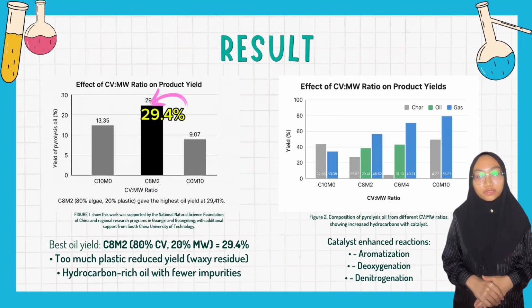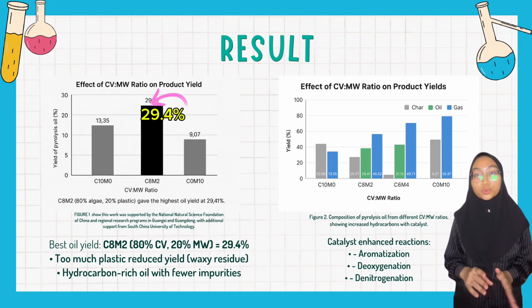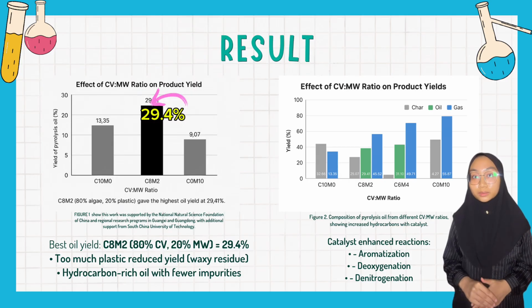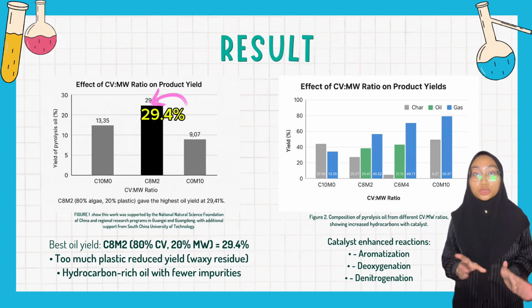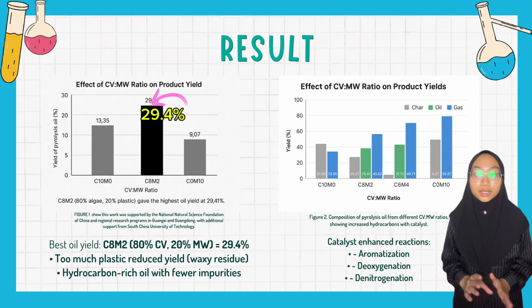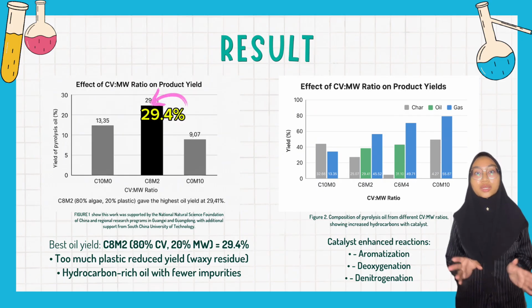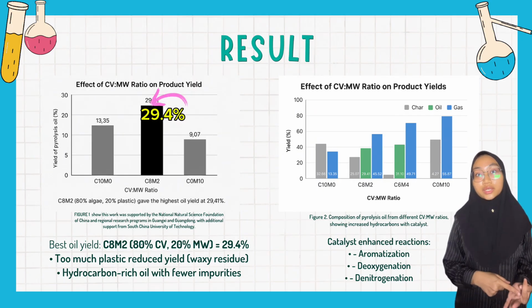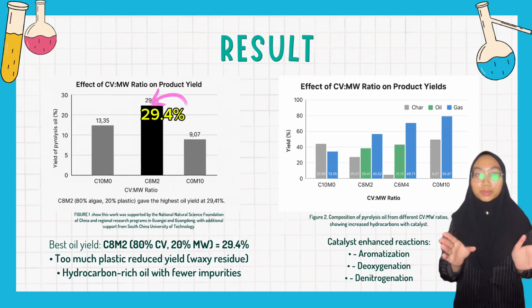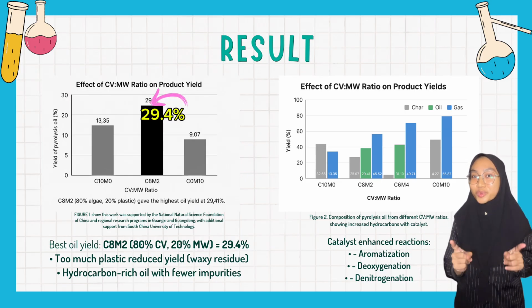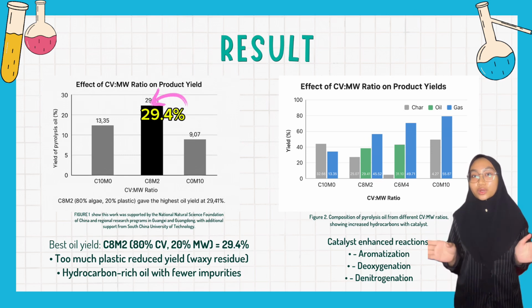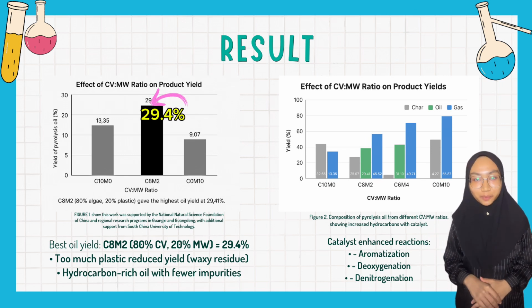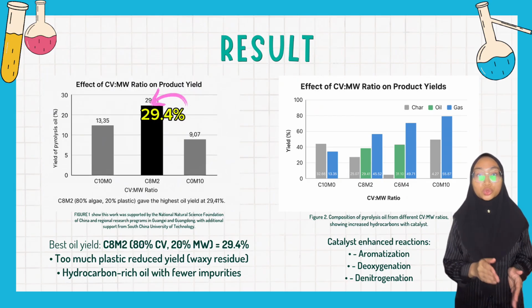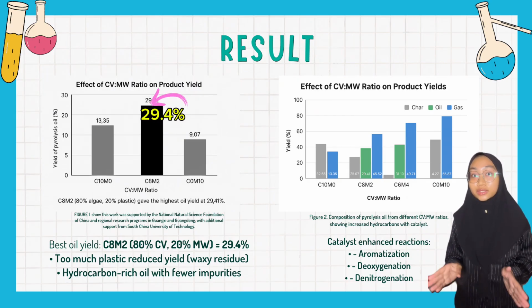With the addition of the ferrum oxide or C catalyst, we observed better microwave absorption, improved heat distribution, and enhanced catalytic reaction. Reactions like aromatization, deoxygenation, and denitrogenation were all improved, which means the oil becomes cleaner and more energy dense. We also noticed that increasing the plastic content too much reduces the oil yield, possibly due to the waxy nature of plastic residues.